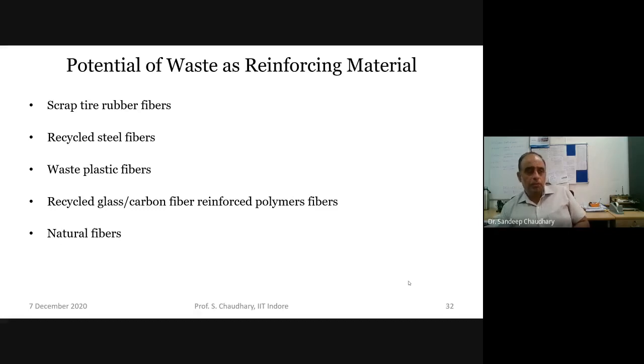Many times, many scholars have a misconception that if I use the fibers in the concrete, then I should get a very high flexural strength. But it doesn't happen most of the times. And some of the quite popular fibers which are available in the market, industrial fibers, if you use them in concrete, you will not find any increase in the flexural strength. So that should be very clear. It's not about the increase in the flexural strength. And when we are using the word reinforcing here, it's not about the reinforcement at the structural level. It is about the reinforcement at the material level, where we are trying to arrest the cracks to ensure proper durability of the concrete.